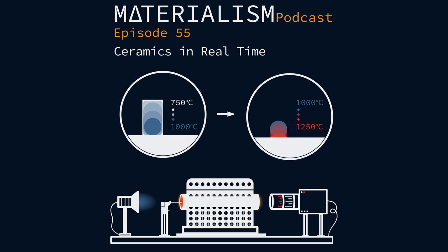For the optical dilatometer, the core idea, which was also patented in 2004, was to motorize the camera. So in optical dilatometer, you have two cameras looking at two tiny, tiny edges of the sample. And you measure the displacement between these two tiny points of your sample. In classical double beam optical dilatometer, which exists since many decades, everything is fixed. So you have the two cameras looking at the two points, the material expands or shrinks. And when the material exits from the field of view of the camera, you're done. The measurement is finished.